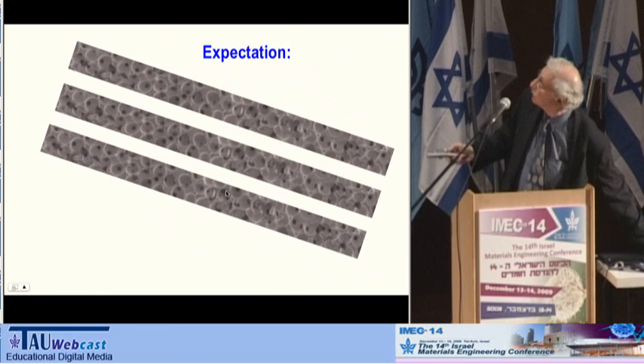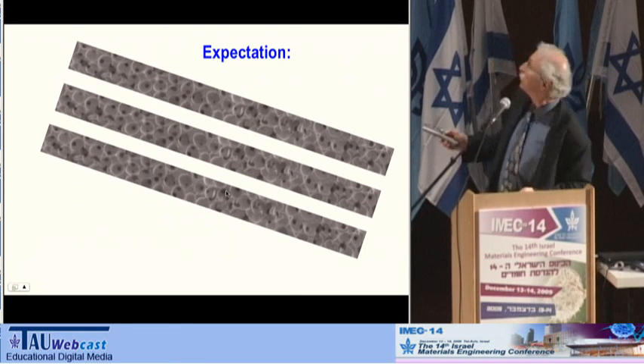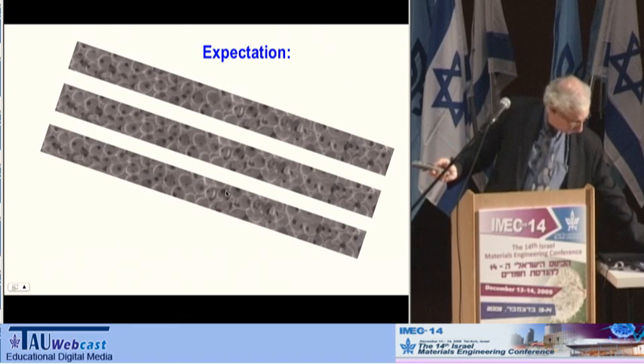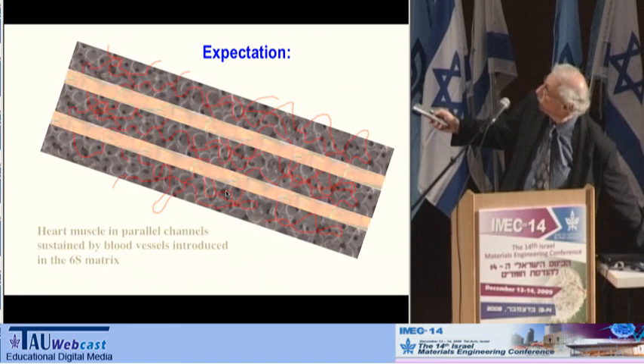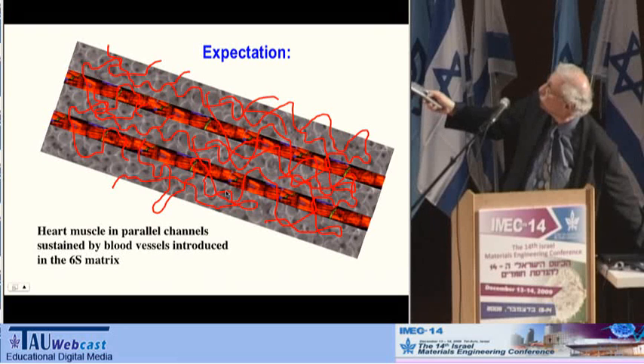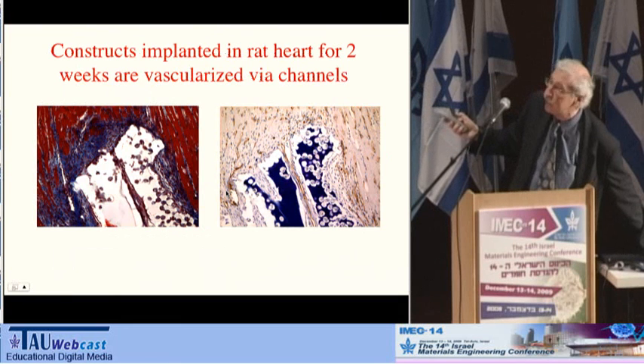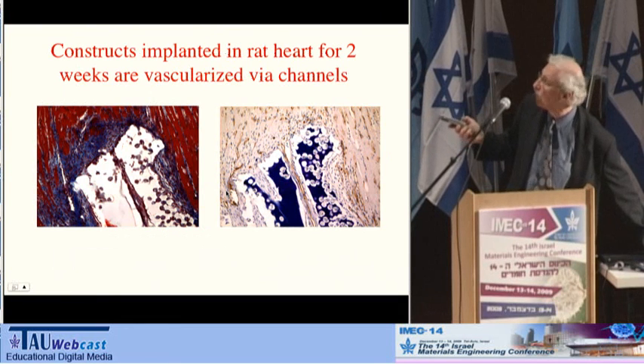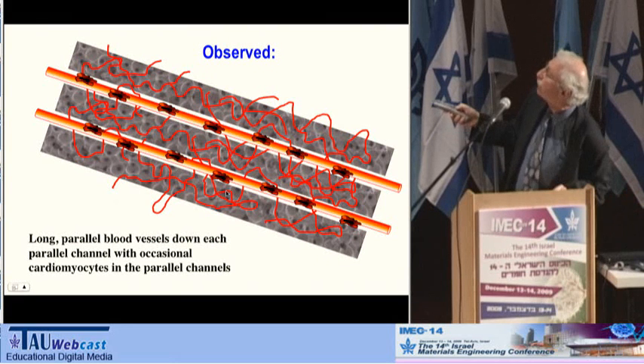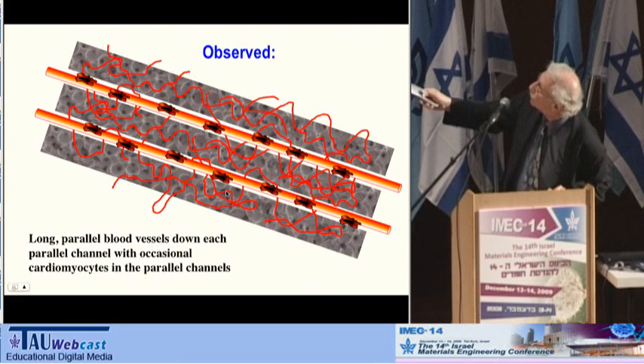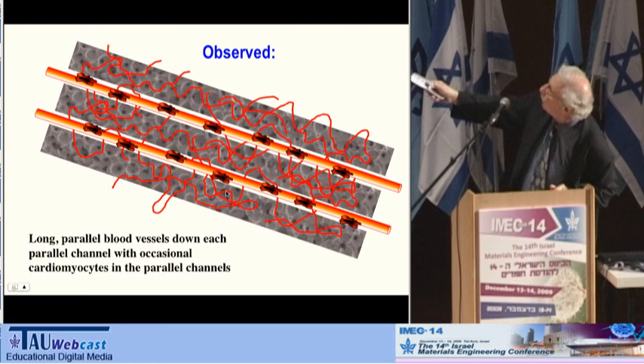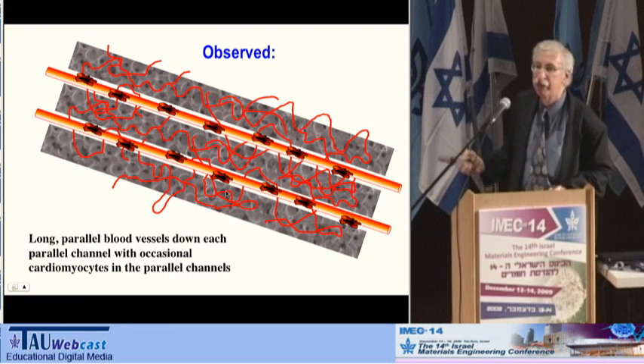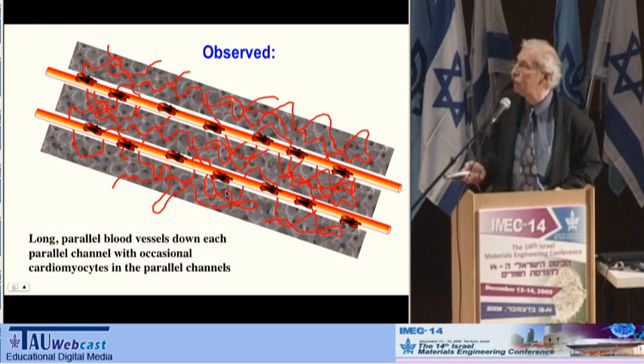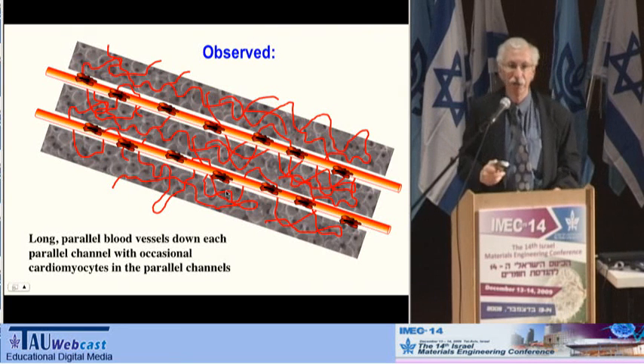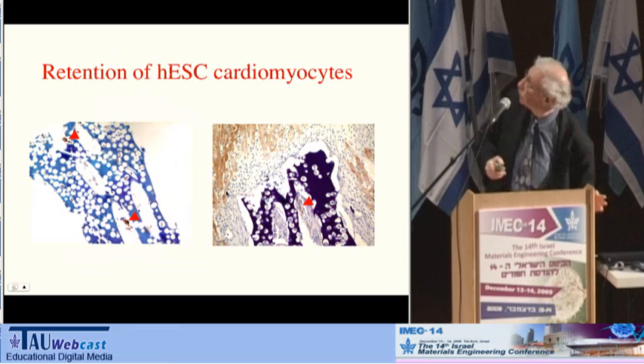And then we implanted it to heart muscle. What we expected to get in these long channels was heart muscle through them and angiogenesis throughout. This is the histology, which I'm not going to go into for the sake of time, but actually what we found was down these long channels, the body put large blood vessels, which were then surrounded by these cardiomyocyte cells. It's a bit of a different reaction from the one we expected, but actually potentially a very good healing reaction. So we're studying this further.